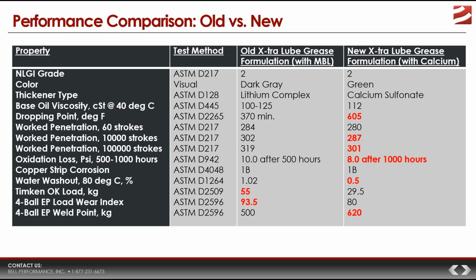They exert a specific standardized amount of force, rotating the balls at a standardized speed for a specific amount of time, then stop it, take the bearings out, and look to see if there are any wear scars formed. If there are, they measure them, put the balls back in, and run the test again. They repeat this at standardized intervals of load — 8 kilograms, 15, 30, 50, 67, 100, 120 — increasing incrementally until there's too much load and the lubricant can't handle it and the balls weld together.